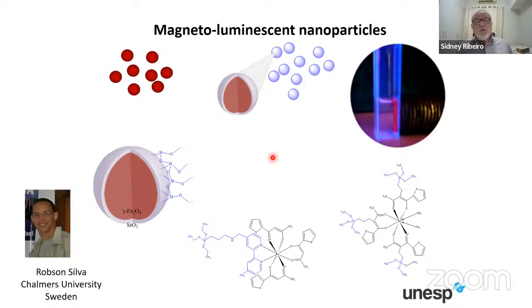Silica can also be used to coat magnetic particles. Marcelo just showed us some examples. So in this case, we used iron oxide, we coated it with silica, and then we modified the surface with the luminescent compounds. So what you see here is a cuvette with the particle suspension illuminated in UV. So the red color you see here is the luminescence of the particles. And we have a magnet outside the cuvette here, just to show that the particles are magnetic. So this is a multifunctional magnetoluminescent nanoparticle.